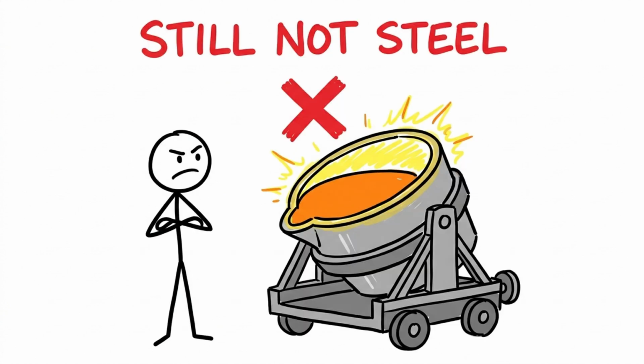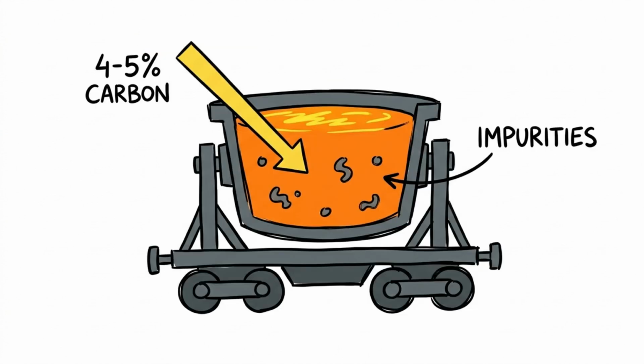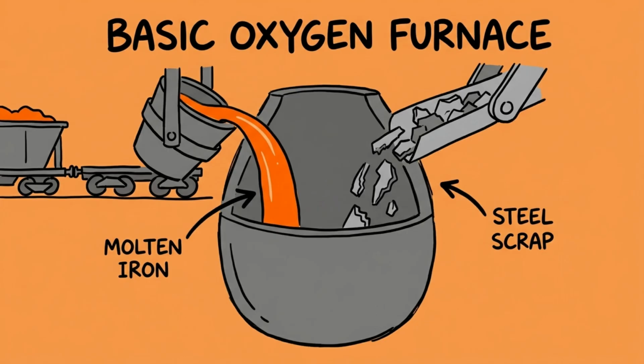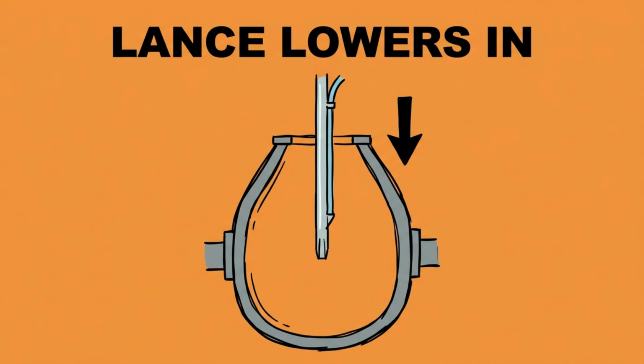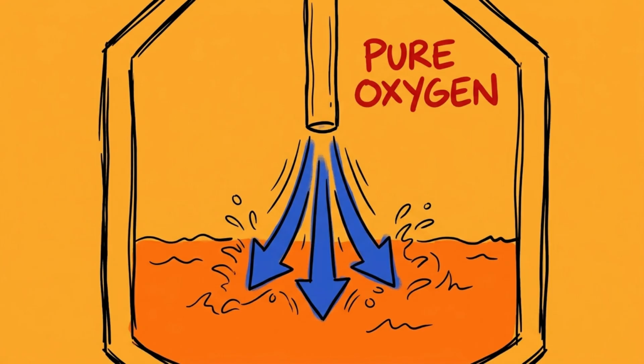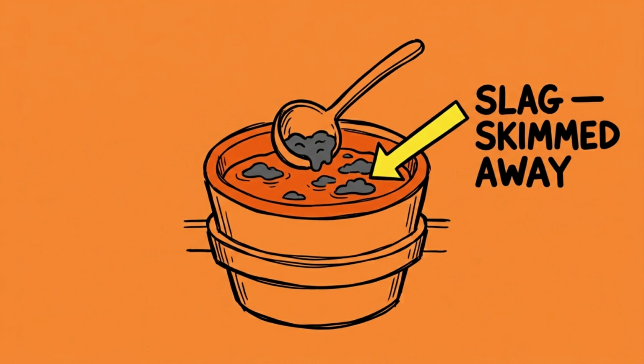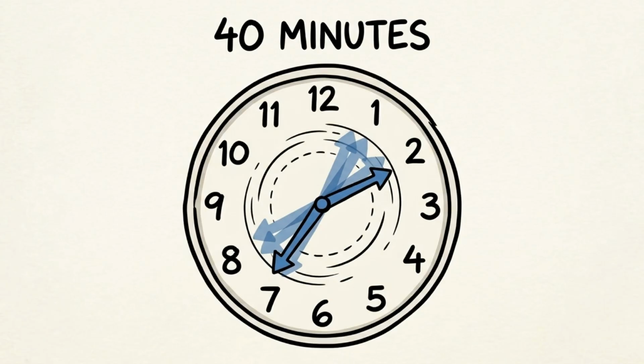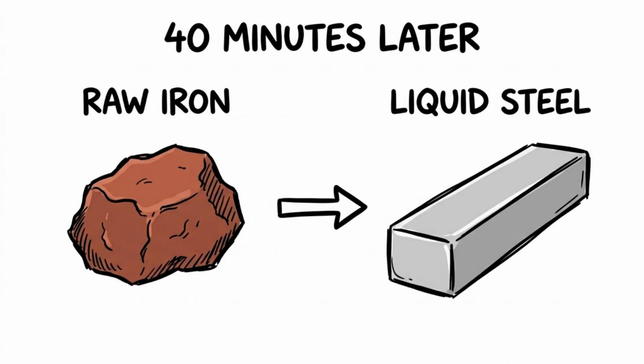But this is still not steel. The molten iron from the blast furnace contains too much carbon, typically 4 to 5%. It also carries impurities. To become steel, it needs refinement. The liquid iron gets transferred into a basic oxygen furnace along with recycled steel scrap. A water-cooled lance lowers in, and pure oxygen blasts through the molten metal at supersonic speeds. This burns off the excess carbon and oxidizes the impurities, which float to the surface as slag and get skimmed away. The whole process takes about 40 minutes. In those 40 minutes, raw iron from the ground becomes liquid steel.